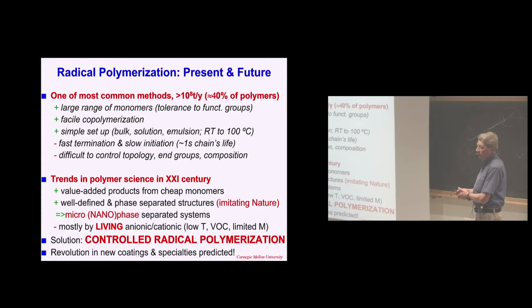You can do it in bulk. This is how plexiglass is made. You can make it in solution. It can be organic solvent, can be water, under homogeneous, but also dispersed media. So all of these emulsions, miniemulsions, microemulsions, dispersion polymerization go here. And typically you run reactions at maybe 60, 70 degrees. So you take the heat of an exothermic polymerization as such. And otherwise you can work at -80 if you wish, and polyethylene is made at 250 degrees. So a large range of conditions.